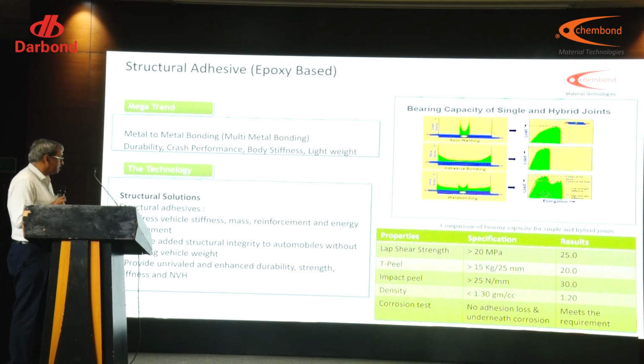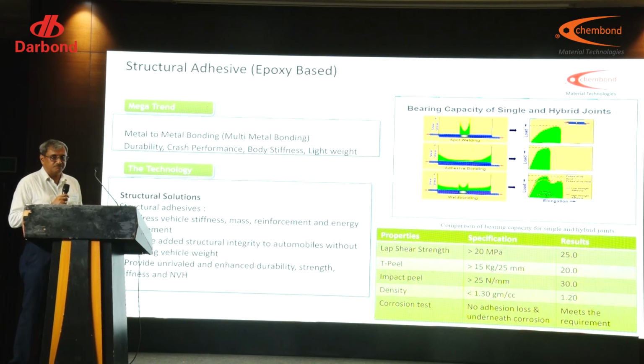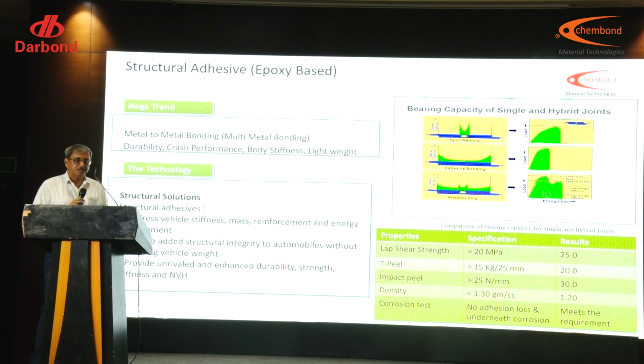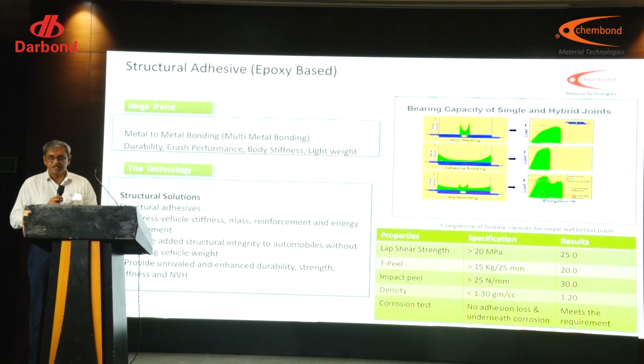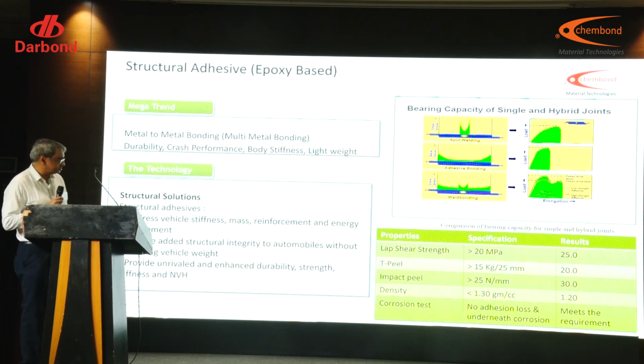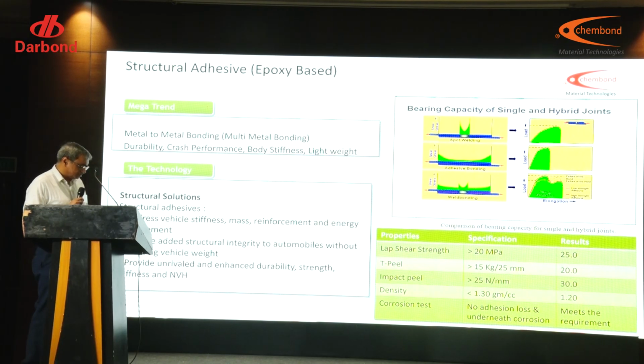We are also in structural adhesive, apart from conventional mastic adhesive and conventional hemming adhesive. Structural adhesive provides good energy absorption, and especially the structural integrity and stiffness required for the body in case of any crash or accident. It absorbs the energy and helps transfer the energy from one part of the body to another, reducing the localized impact. It has a very good combination of strength and elongation, very high impact peel, and the strength properties surpass the specification available for structural adhesive.